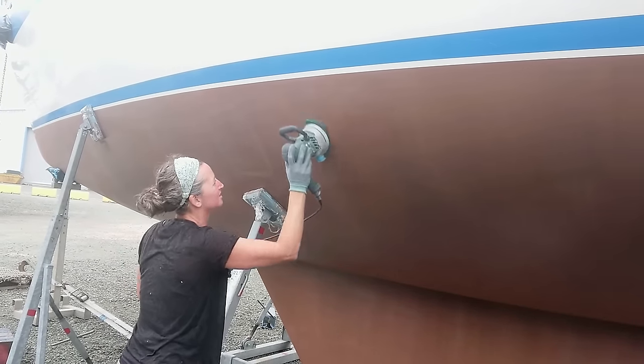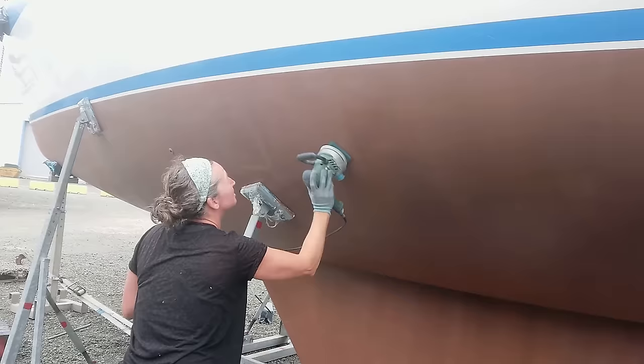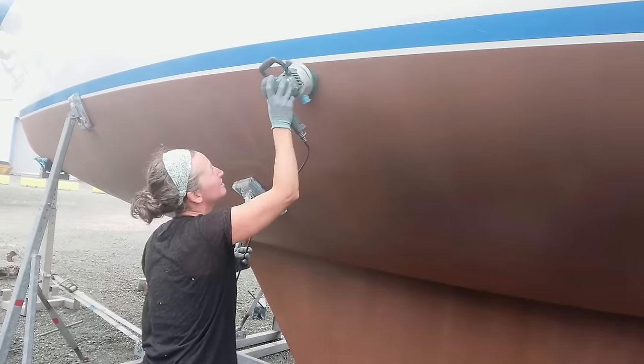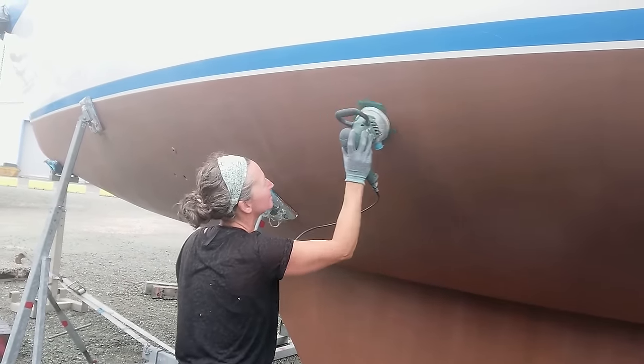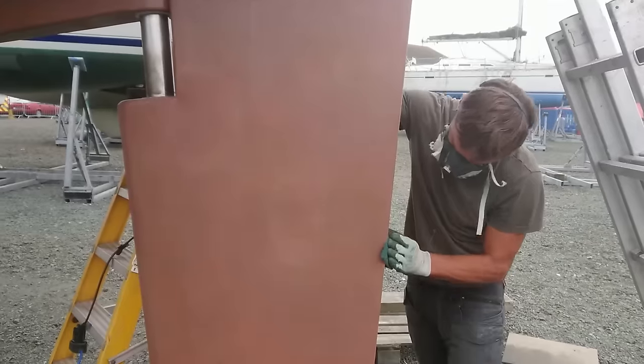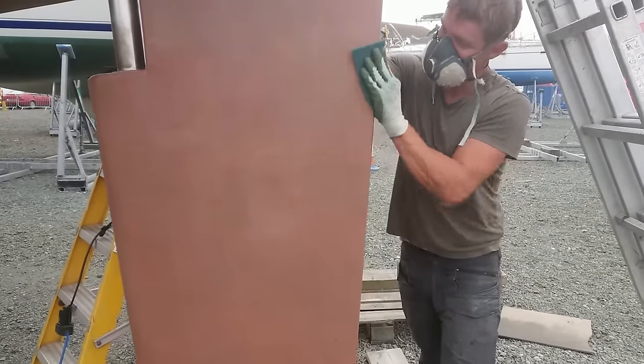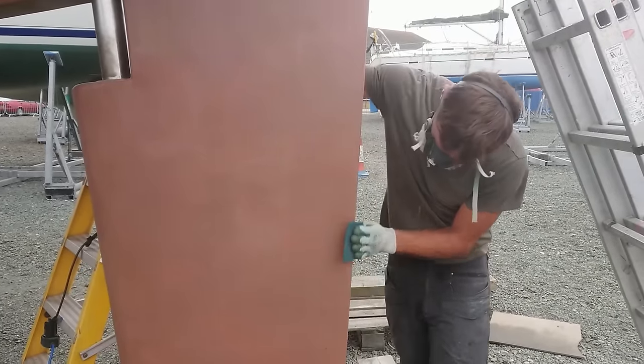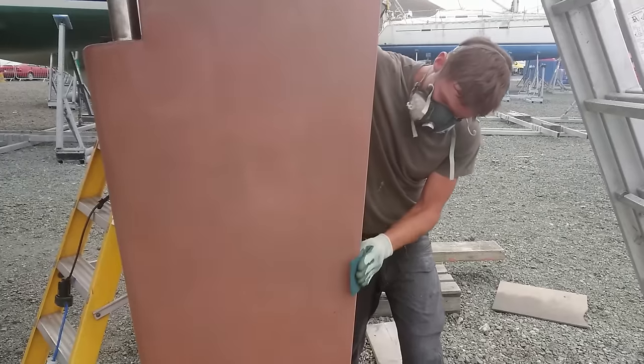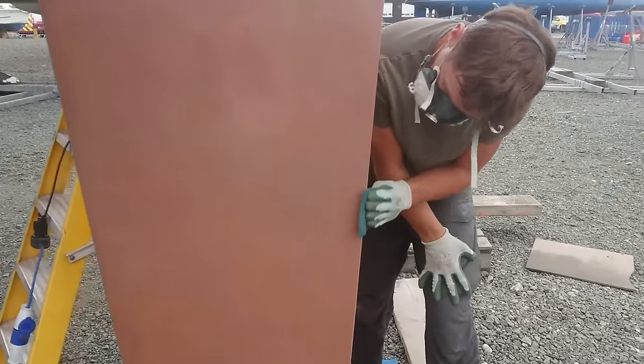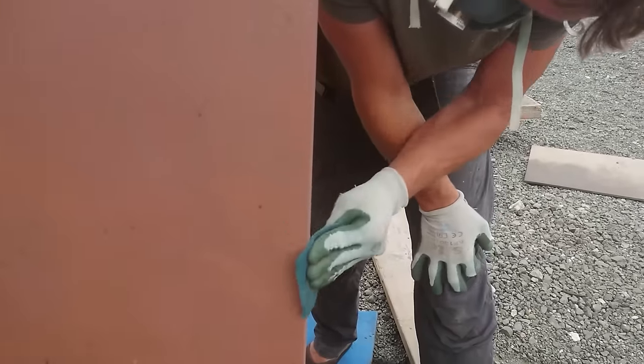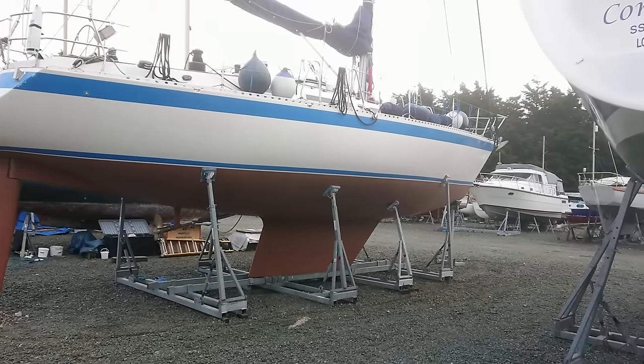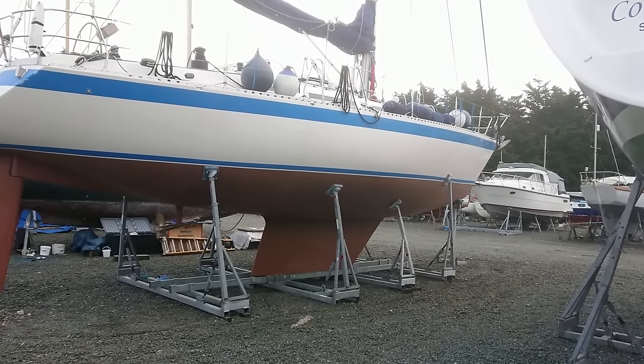While we were researching this, we'd seen videos and read stories of people applying copper coat and it unfortunately not being that successful for them. But copper coat's basically just a way of keeping copper exposed on the outside of the hull, and sailors have been successfully using copper as an antifouling coating on boats for over 350 years. If you stick to the recommended directions, there's not a lot to go wrong. You've just seen it's not a difficult process.